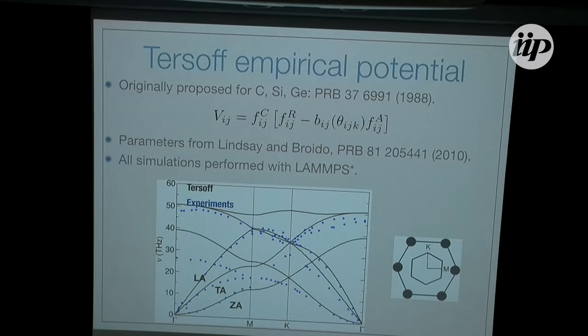The problem with that is just computational, right? So essentially, the calculation of the forces with the Tersoff potential scales linearly with the number of atoms. For graphene, we use parameters obtained by Lucas Lindsay and David Broido. They published it in 2010. Lucas is going to be here next week, so if you're still around, you can see what he has to say about his latest project. And we did all of our simulations with LAMMPS, with a small exception that I'm going to bring up in a few slides.